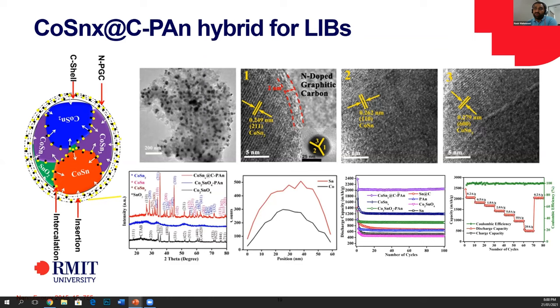So if you look at the structure here, you will see that we have different phases, experimentally observed. We did XRD, and we also confirmed with EDX that the cobalt and tin are distributed as we want in the structure. Then we did electrochemical energy storage in the lithium ion battery, and we found that it has a higher storage capacity than the previous study, and a better rate capability: whatever rates you are giving it, if you are shifting higher, it returns to what it should do. So such a 3D design with internal engineering of the particle is very useful.